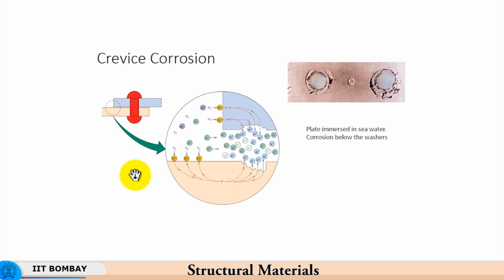Wherever there is less oxygen available, you have entrainment of these aggressive chloride ions, which will start eating into the metal over here, and there is nothing else to prevent that. So, that is the reason why we get what is called crevice corrosion, especially when the two metals are bare. So, if they had been painted here, if this layer had been painted and that layer had been painted, then it could have been prevented. But normally what happens is when we tighten a bolt, for example, let us say these two plates are being fixed by a rivet and there is no paint in between,